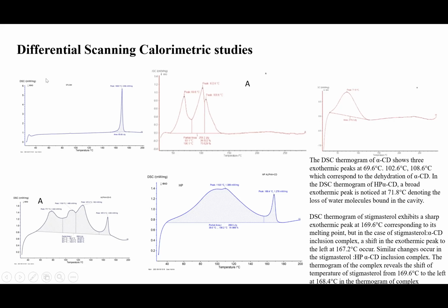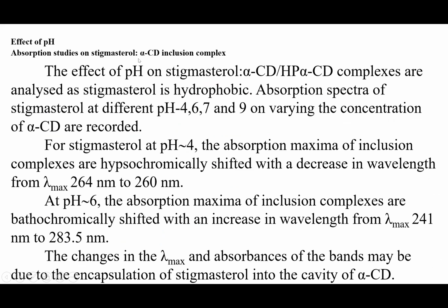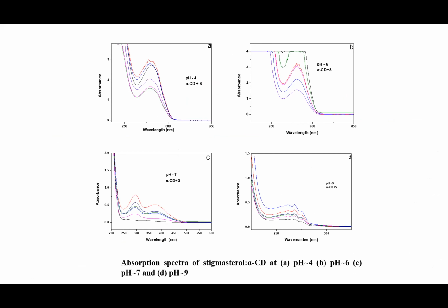And here, the effect of pH, absorption studies on the stigmasterol alpha CD inclusion complex. So here, as I mentioned, I have varied the pH value from 4, 6, 7, and 9, keeping the concentration of stigmasterol constant and varying the concentration of alpha CD. Here also, I have taken UV studies to confirm and to calculate the binding constant for these different pH values. So these are the inclusion complexes for alpha CD. This is at pH 4, this is at pH 6, and pH 7 and pH 9.